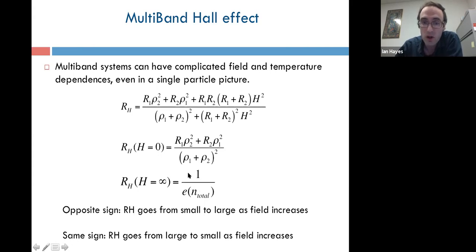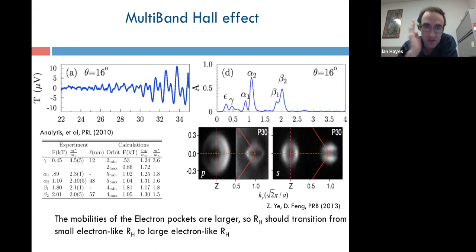You'll go to a very large RH as your N total, electrons minus holes, goes towards 0. So the generic thing you'd expect for this system is for RH to start out small and get large. If you were to have two carriers of the same type, then you'd expect the opposite behavior. It starts out high and then gets smaller. And because Barium-122 has 4 bands, this is a possibility, but there's quite a bit known about the band structure